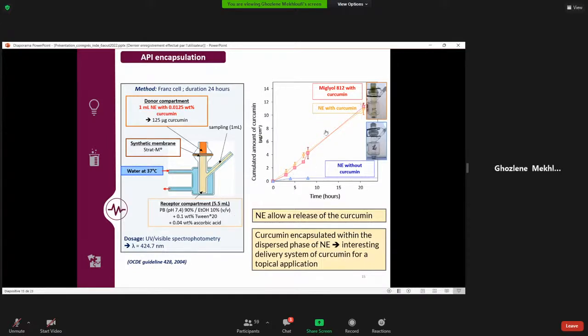We followed the diffusion of curcumin from two different systems: the curcumin encapsulated into the oily phase of the nano-emulsion, and the curcumin solubilized directly in the oily phase. As we see here on the graph, the accumulated amount of curcumin increased over time, and thus curcumin diffused through the synthetic membrane, both from the nano-emulsion and from the oil in which the curcumin has been solubilized. So the nano-emulsion effectively allows a release of the curcumin.